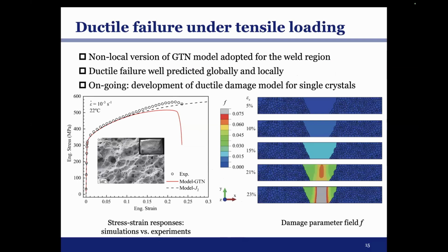Another thing that we have also tried to do is to simulate the ductile fracture of this cross-weld specimen under tension. So we use simply a GTN type model for only this middle part, the weld region, and we try to run the simulations, and we see that in terms of the stress drops, we can predict them with this model, and we also predict the evolution of the damage parameter in this middle part.